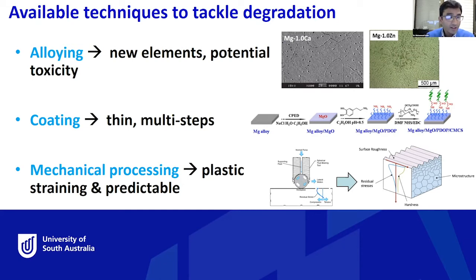The third technique also being studied is mechanical processing. Instead of adding a new coating layer onto the substrate, why don't we just process the substrate material by mechanical processing, doing some plastic deformation or straining of the material microstructure, so that you can still get some benefits in terms of corrosion resistance and other mechanical properties. One of the processes in this regard applies a microstructural change by mechanical treatment, which could be machining of the substrate, grinding, or shot peening. There are different techniques, like ball burnishing or laser peening, being used to improve the corrosion resistance without using alloying or coating.